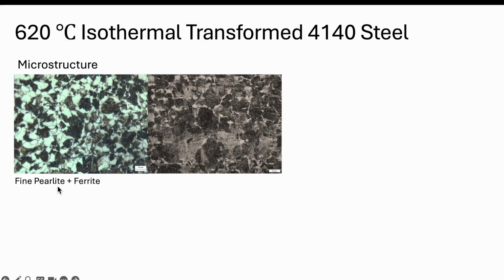So again, I mentioned the fine part. That means the spacing is very small. A lot of times, instead of being visually distinct layers, you might actually just see one color because the layers are so fine. Every once in a while, you can see some differences, like over here, and over here as well. It looks like there's some layers, but sometimes with the fine pearlite, unless the etching and so forth is really great, you don't see those layers. You just see a light and a dark. But this is in fact fine pearlite plus the ferrite that we see here.